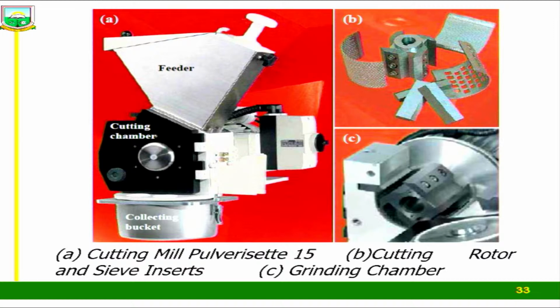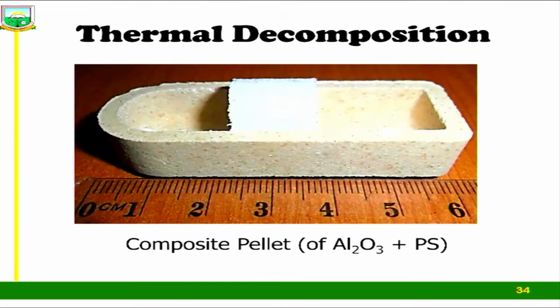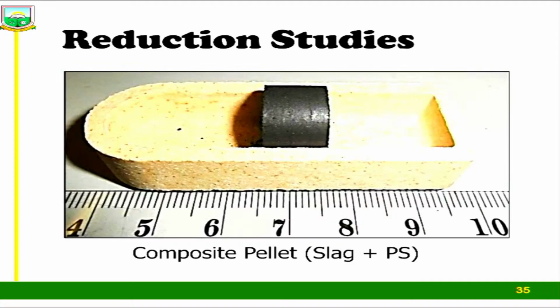In Ghana, one other thing is that you can also put these plastics in liquid nitrogen. That will cause them to become brittle, and then you can crush them. When we did this, we were able to crush them, and then first we did some thermal decomposition studies, followed by our reduction studies in a horizontal tube furnace.